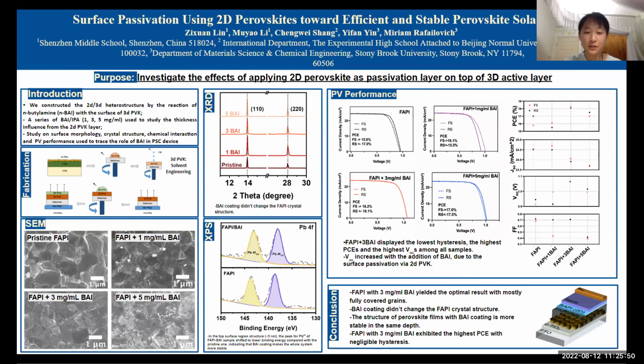For the fabrication process, we first made a substrate composed of FTO glass, compact, and mesoporous titanium dioxide. Then we used solvent engineering to construct a 3D perovskite. During the process, we did anti-solvent dripping using chlorobenzene, followed by annealing. Next, we spin casted 2D ligand onto the 3D perovskite to react and form a 2D perovskite, followed by annealing as well.